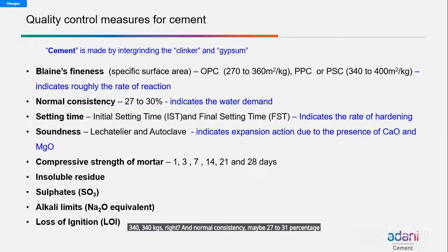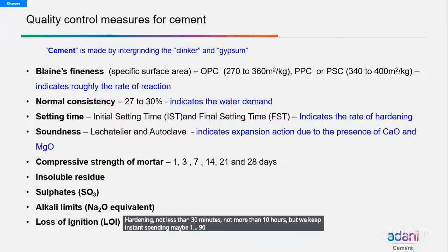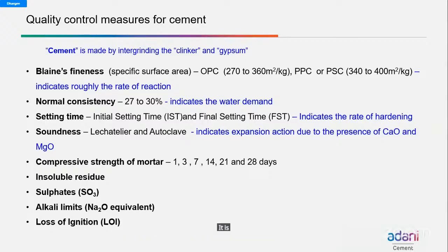Initial setting time indicates the rate of hardening, not less than 30 minutes and not more than 10 hours. But we keep initial setting maybe 90 minutes to 120 minutes. Final setting time may be 180 minutes to 200 minutes. We are keeping this in our lab, in all our cements. Soundness is the expansion. We have to find the expansion. It is mainly contributed by lime and magnesium oxide.